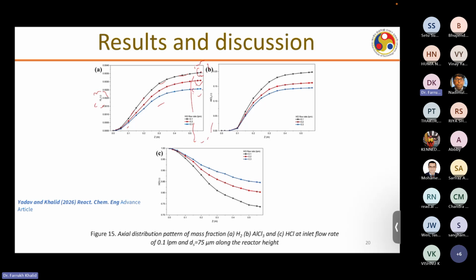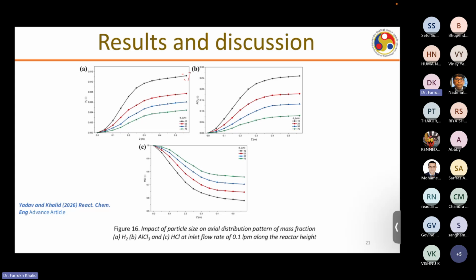However, the HCl at the top is not there because it has already been consumed. At the bottom, since we are feeding our reactor with the HCl gas, HCl has a higher concentration initially, but as you go up, there is no more HCl left because it has already been consumed. This is the similar pattern we observe as you go up the reactor. Similarly, we also wanted to see the effect of particle size on this distribution. It has been observed that the smaller the particle, the more hydrogen you can produce. So it clearly shows the impact.